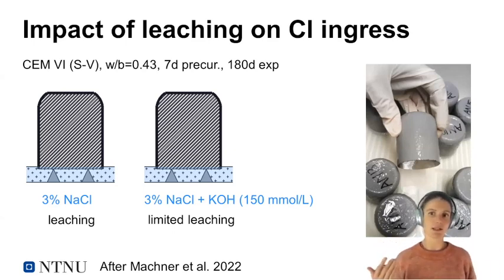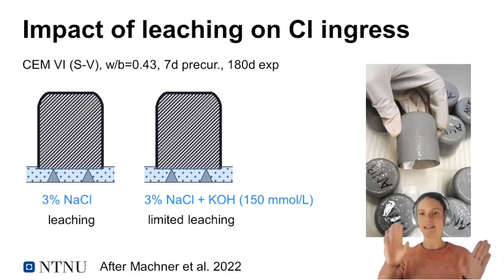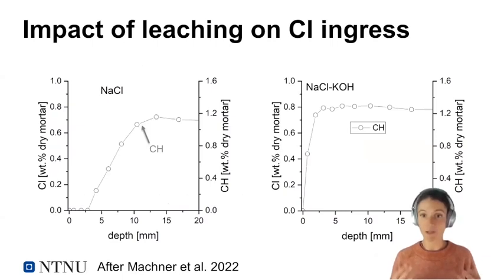Exposure solutions were exchanged weekly, but in one we had just sodium chloride, and in the other we had added additional potassium hydroxide to limit leaching. So let's look at the results. We start with Portlandite profiles, which are an indication of leaching. We saw that's one of the solids that's actually dissolving first when you have leaching.